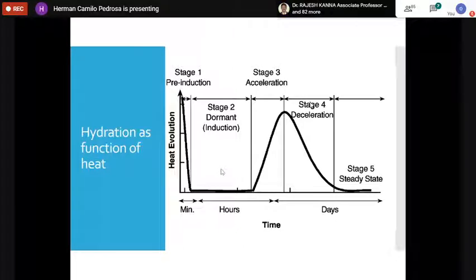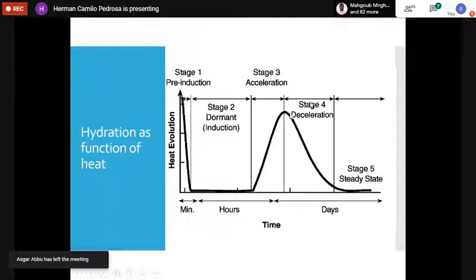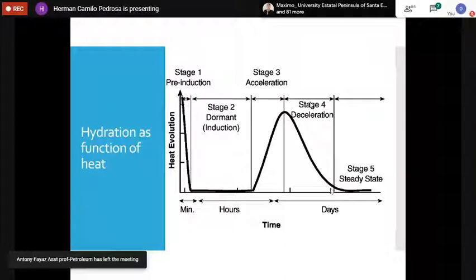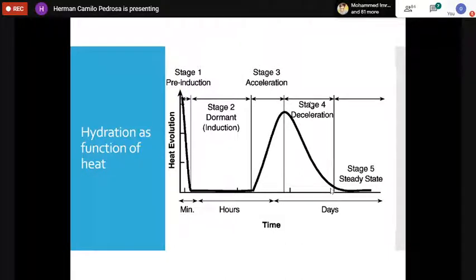Well, I'm not going to give you the full chemistry of that, but what happens pretty much is that the ions will start to, let's say, reaccommodate. And after that happens, we have the acceleration part. And you see a bump here, that's because it's an exothermic reaction. So when the cement starts to become CSH, it will release heat. And then we have this acceleration part. That means that it has already reacted. We already have a set cement or a hard paste. And then we will start having the solid cement that we know. And that will take a couple of days.